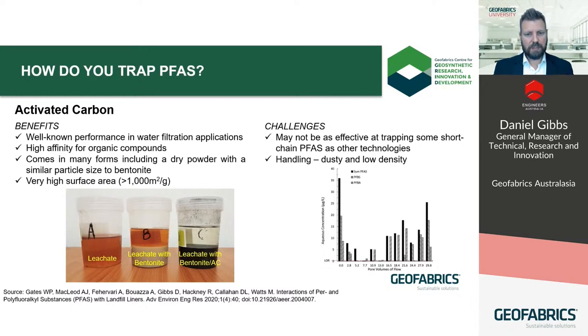The extent of the adsorption is proportional to the specific surface area. So having an activated carbon with a very high specific surface area helps with total contaminant loading capacity and also the speed of uptake. As you can see in the photo here of these pre-fluid loss samples, which were mixed and aged, the activated carbon bentonite blend on the right was far more effective at stripping out a range of contaminants, including PFAS, from the leachate than the bentonite itself. Given the increased mobility of some of the shorter chain PFAS, one of the challenges with this product is that some activated carbons, at least, may not always effectively capture and hold onto some of these shorter chains to the same extent as the longer chain variants.